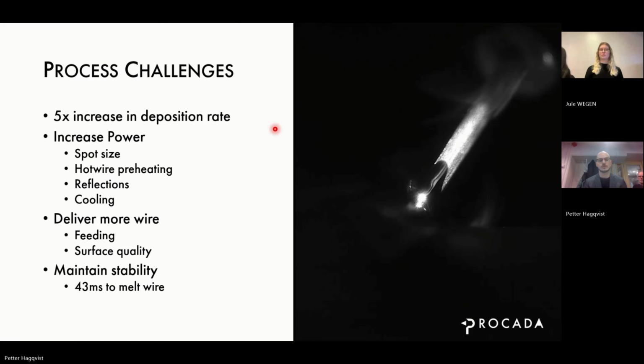Basically, we are introducing maybe, in the worst cases, 15 kilowatts of power into the processing chamber, which means that unless we want everything to get hotter and hotter, we need to also get rid of 15 kilowatts from the processing chamber. So that means that everything that went in there, which isn't supposed to get hot, must be cooled and must be water cooled. We spent very much effort onto this.